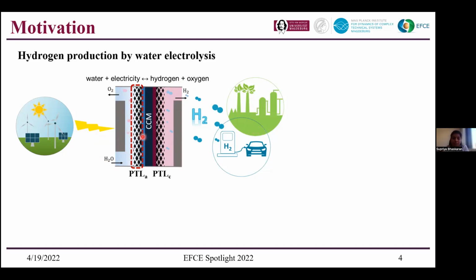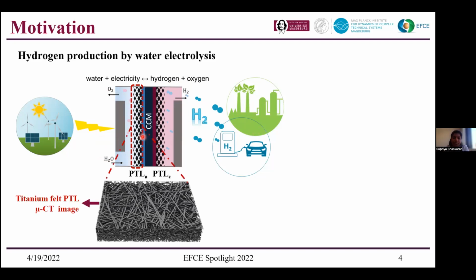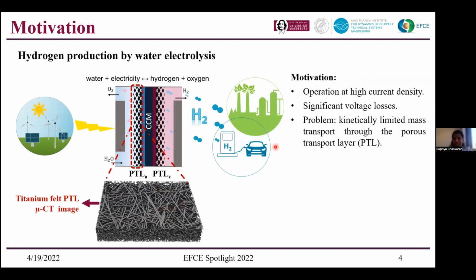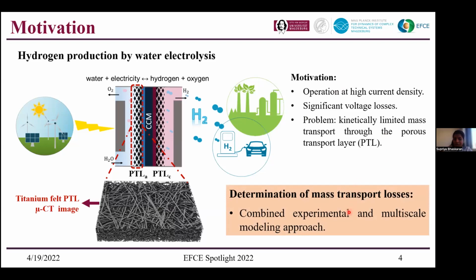This porous transport layer would be our main focus, because it is a very tiny structure which is used to flow the water from the flow channel to the catalyst layer, and also as a pathway for the removal of oxygen. The main thing that we deal with here is the titanium felt porous transport layer. This is an image that we obtained from our MicroCT. The major motivation here is to see the operation at high current densities and significant voltage losses. The main problem here is the limiting mass transport through the porous transport layer. So how do we determine this mass transport? Here we mainly focus on our experimental and multi-scale modeling approaches.